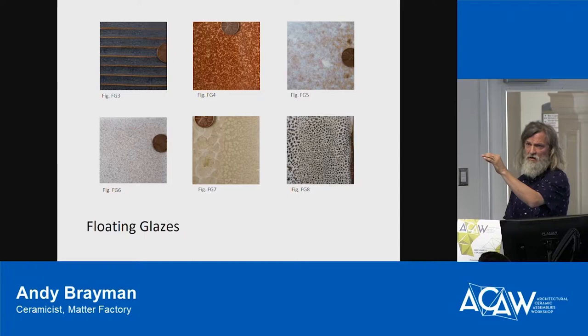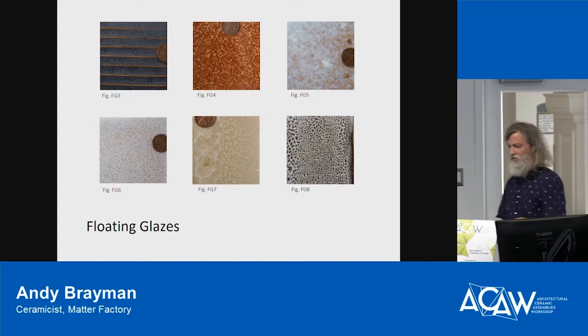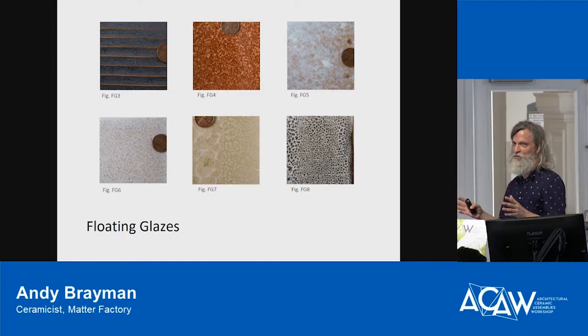And when you really work with glaze a lot, early on you figure out that what you're putting it on can have a huge effect on it. Whether the surface is flat, whether it's vertical, whether there's texture, it can have wildly different impacts on how the glaze melts and how it moves and what it looks like in the end. And so lots of artists really capitalize on that. They'll know the glaze they're going to use, they make the form. For beginning people in ceramics, if you walk into any ceramics 101 class, there's the bisque ware. There's a shelf that's not glazed. It's usually full because the people make the thing, it looks so good when it's wet.